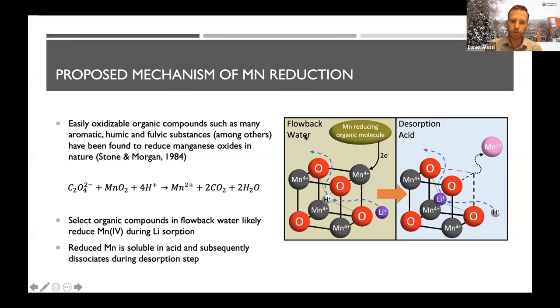So you can imagine here, I'm calling it flowback water here, but here's the brine in which the manganese material is placed. And this is the lithium loading step, right? So it's sitting in the brine, there's lithium in the brine, it goes into the ion exchange site in the mineral, and in this case, a proton is kicked out. At the same time, we've got these organic molecules, right? A ton of them, because this is a brine that's been in contact with hydrocarbons across a wide spectrum of chemistries. So some of these organic molecules are able to reduce the manganese. So again, there's electron donation, say 2 electrons, which reduces this manganese 4 to manganese 2, and it may very well stay associated with the structure at that point.